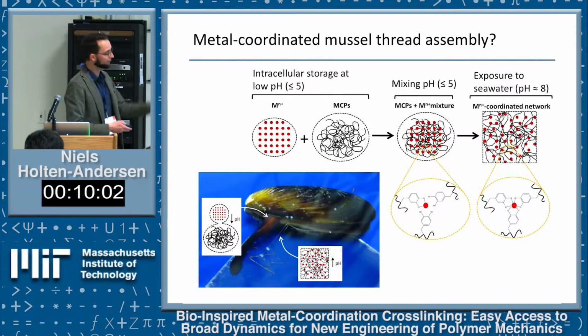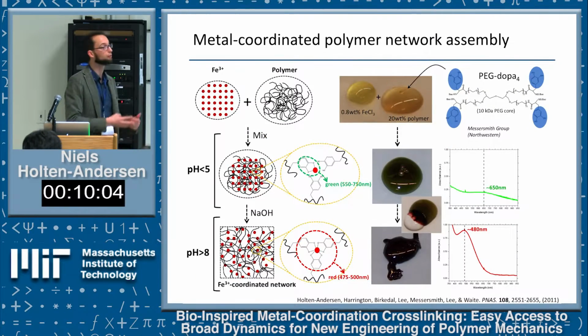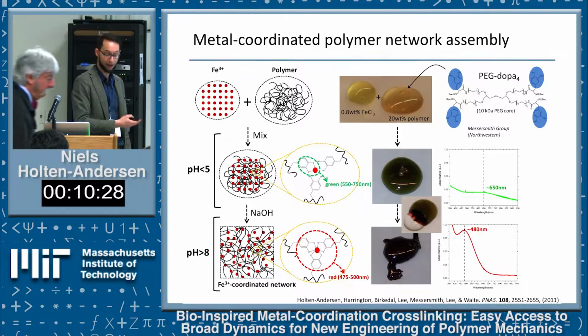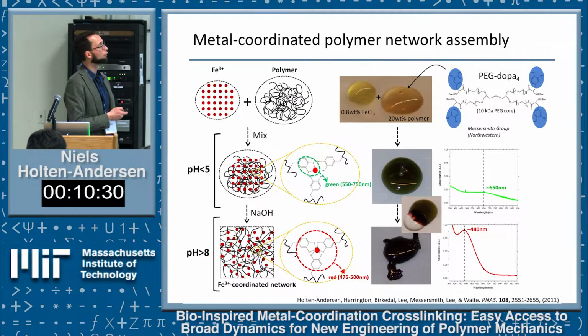To mimic that in a much simpler system, we've been playing with polymers that are soluble underwater, called polyethylene glycol polymers, which are widely used in medicine and medical materials. These have been functionalized as a 4-arm polymer with 4 metal-binding ligands. All we do is take some of that polymer, dissolve it in a little water, and take our choice of metal salt—we started with iron chloride, since that seems to be what the mussel prefers, and it has high binding affinity. Then we mix those two fluid droplets together.